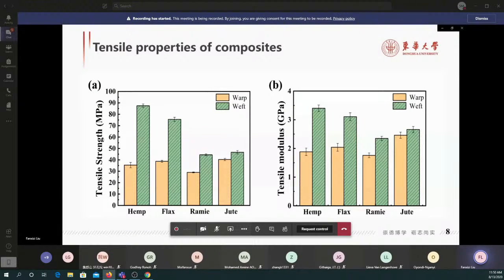It can be seen that the strengths and moduli of the 4 composite materials were larger in the weft direction than in the warp direction, because the weft yarns were thicker and the weft fabric counts were larger than those of the warp. The tensile strengths and moduli of the 4 composite materials were in between those of the vertical and horizontal strips of the wood. The crimps of warp and weft yarns in the composite could reduce the utilization of the strengths and moduli of the yarns in the composite.